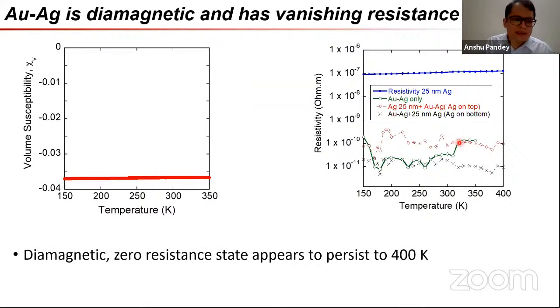What we found when we made this material, and this was done by Dev Kumar Thapa long back, is that this material is diamagnetic and appears to have a vanishing resistance, even all the way through to 400. So our original observation suggested something which seemed to be around 3-4% as diamagnetic as a regular superconductor. That's, at least in our attribution, probably because this is made up of nanoparticles, and when you have nanoparticles, you cannot get the susceptibility absolutely to that of a full diamagnet. We felt that that might be the issue, but that is still open to question.